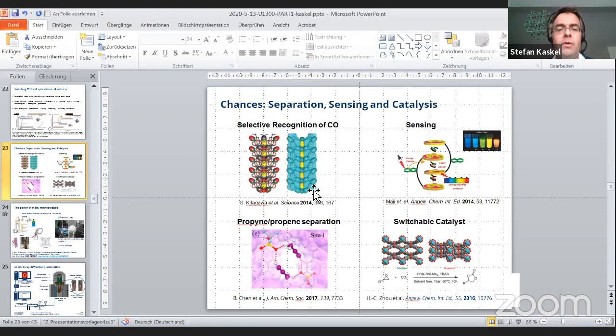So here it has been used for the separation of CO and nitrogen. And the mechanism is that there's a copper center and the carbon coordinates to the copper from the CO molecule, because CO is a donor also, while N2 is a very weak donor. And due to the coordination, the channel changes its structure and opens up the MOF. So this has not been used for sensing applications, as far as I know, only for the separation. And the separation factor was above 100.